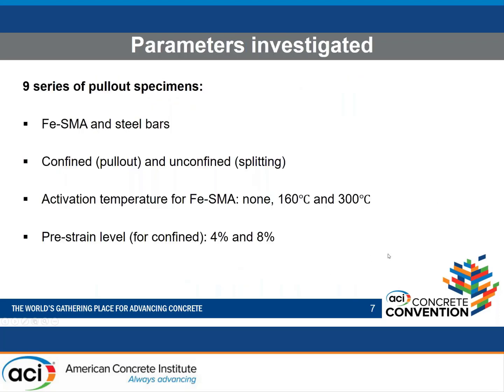So, the different parameters investigated in this study: we did 9 series of pull-out specimens with SMA bars and steel bars, again, iron-based, of course. We had confined specimens, which we wanted to fail by pull-out, and unconfined specimens, which we wanted to fail by splitting. Since the temperature effect is very important, we also considered the activation temperature effect. We considered no activation temperature at all to understand the fundamentals of the bond properties of this bar. And then we considered different temperatures which were reported in the literature for this specific type of bars. As I said, the bar is typically used by pre-straining first and then activating it using temperature. So we considered two pre-strain levels, 4% and 8%. Again, those values are reported for this specific material in the literature.